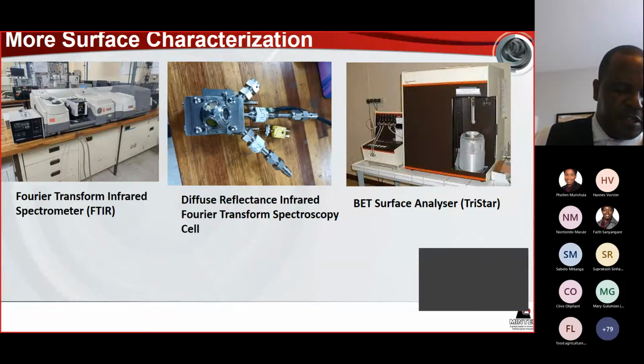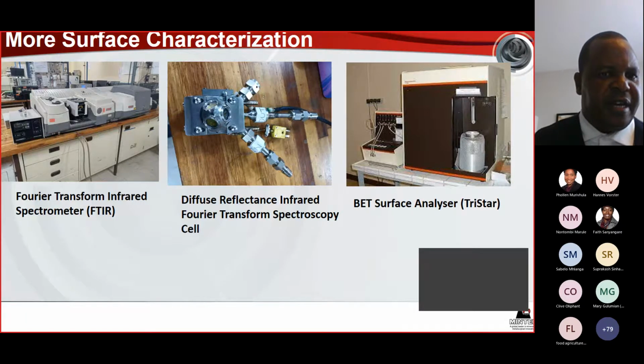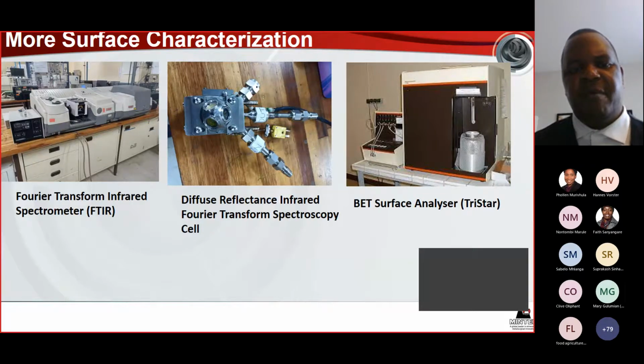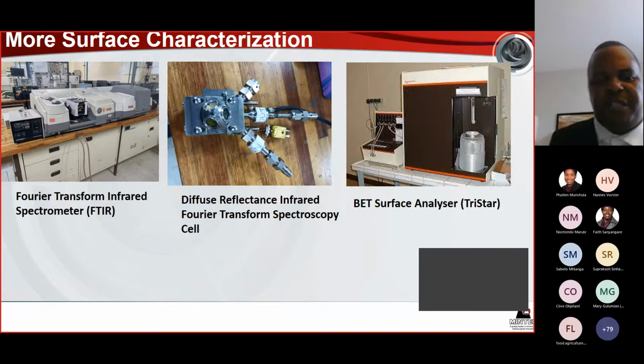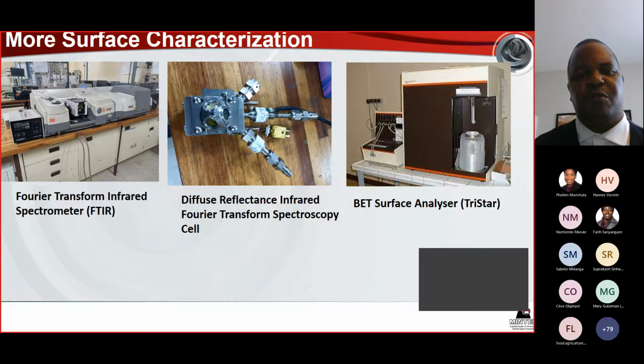And I think to give you context as to some of the things that you may be able to do is, of course, where you have drifts, I think just kind of imagine when you're trying to look at certain materials, maybe let's say for this case, indium nitride as nanowires, and you're trying to detect as a sensor device, say some carbon monoxide or something like that. So to determine the interaction between your material and the gas molecules, whether these be in the form of physisorption, or it could be in the form of chemisorption, you can determine all that using drifts. Which is nothing but diffuse reflectance infrared Fourier transform spectroscopy. So that helps you really to get more sensitive information than you would otherwise get from your typical FTIR. So that's important to have that.